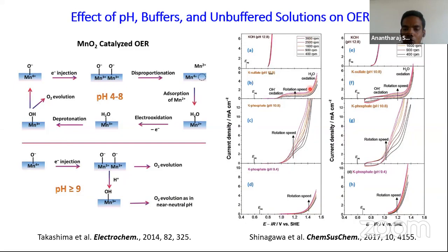So when they increased rotation speed, they observed this kind of peak, which is totally strange to observe in water oxidation reaction, because such a CV or LSV is not usually seen in water oxidation and reduction reactions. They showed that at this pH, when the solution is unbuffered, we have two different reactants, namely hydroxide and water, and hydroxide is easier to oxidize. That's why the oxidation of hydroxide occurs at very low overpotential. But once the hydroxide oxidation is completed, and when we reach this potential, water oxidation begins. So the nature of the solution we use, whether it is unbuffered or buffered, matters.